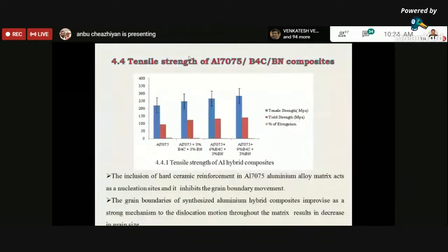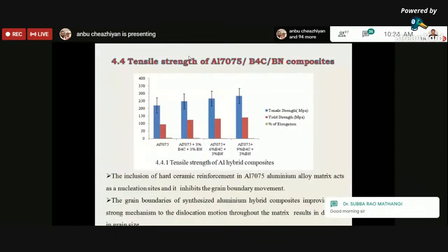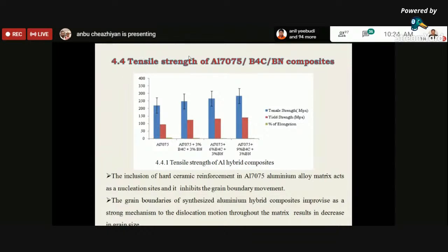Next, we go for the tensile strength of aluminum hybrid composites. It has been observed that with the increase in reinforcement, the ultimate tensile strength increases and the percentage of elongation is reduced. This occurred due to the strengthening mechanism, adequate load transfer between the matrix and reinforcements, the Orowan strengthening mechanism, and finally the grain refinement and dissimilarities in the thermal expansion of the synthesized composites. So here the inclusion of secondary reinforcements provides heterogeneous nucleation sites, and hence the further deformation of the hybrid composite has been increased significantly.